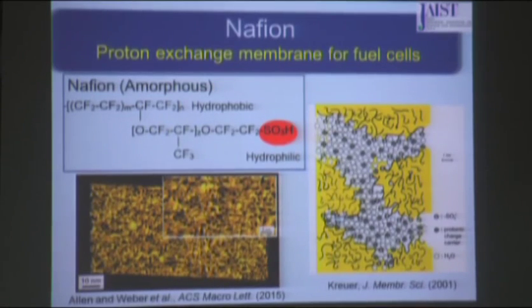Okay, let me introduce Nafion. This is a very commercial, normal fuel cell material, already very commercialized. It is the proton exchange membrane for fuel cells, and the chemical structure is shown here. The main backbone chain is hydrophobic, and the side chain is hydrophilic. So we can have phase segregation between hydrophobic and hydrophilic parts. At the side chain, you can see the red one. This is the sulfonic acid group, the proton source. So this membrane can absorb water.